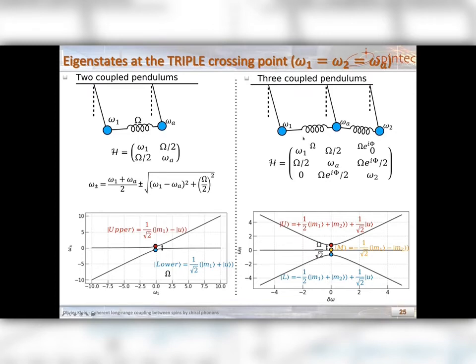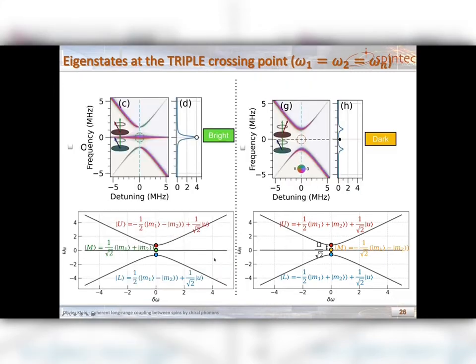You can expand the system to three pendulums. The Hamiltonian is a little bit more complicated, and we now introduce the possibility of having the off-diagonal element being positive or negative by introducing a phase phi here that can be 0 or pi, depending on whether the mode is even or odd. Okay, so you can look at the splitting now. It's a three-level system. And at the triple crossing point, what is interesting to see is that the middle mode, M1 and M2 are out of phase in the case of even mode. And for the odd mode, actually, it's the opposite, okay?